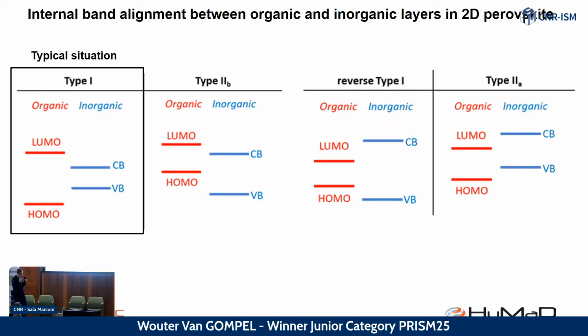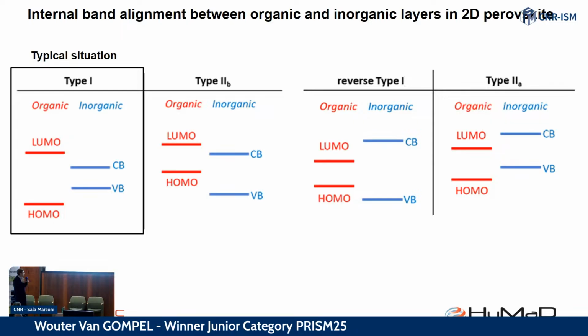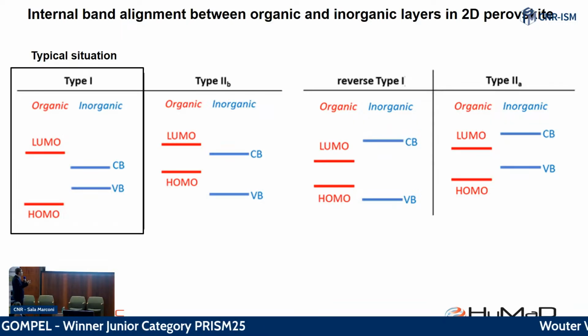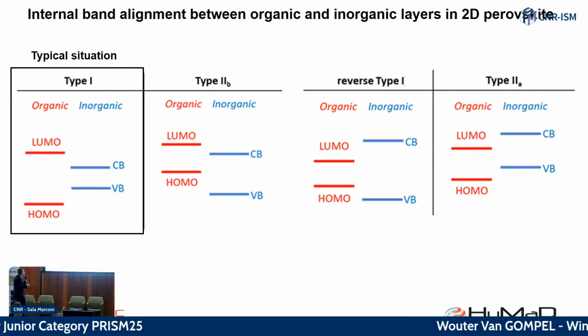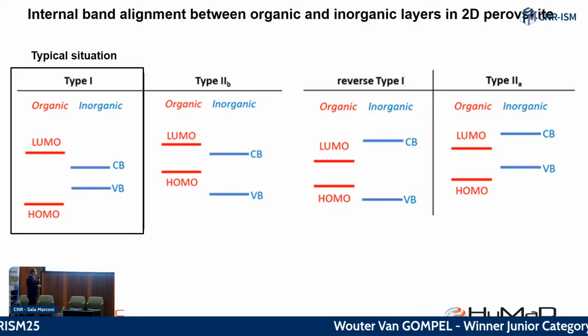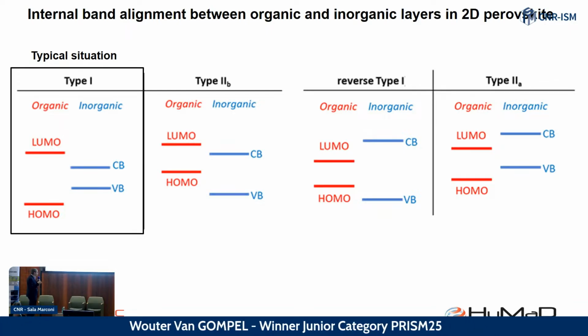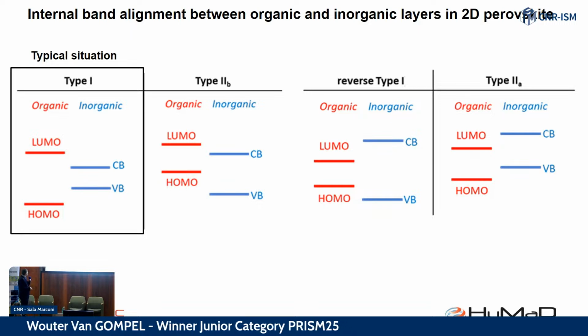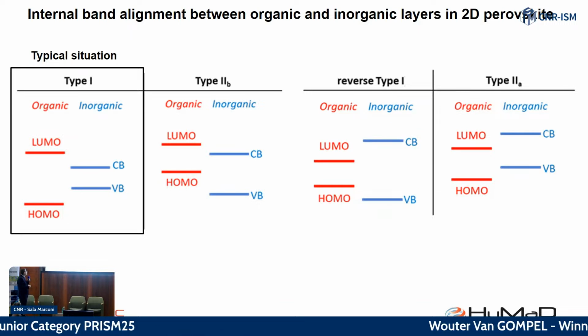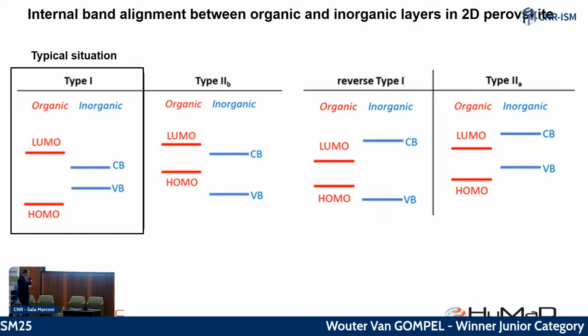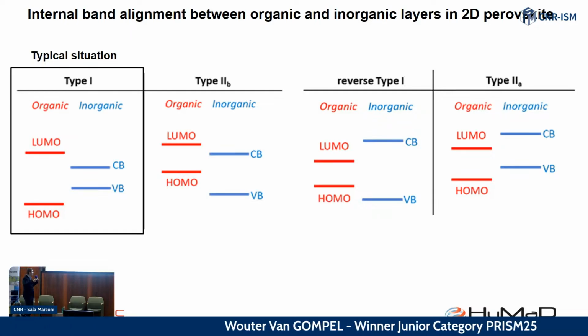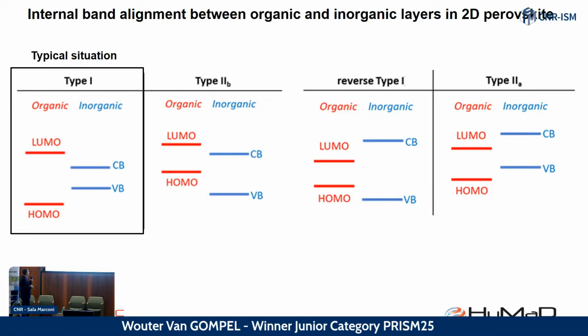But by carefully tuning the composition of the organic and the inorganic, you can get all the types of alignment that you also have in the typical heterostructures. You can think of it as a kind of heterostructure, but then internal to the material. Most are the type 1, but we also developed a couple of them that are the type 2 interface, where you get really separation of the hole and the electron over different layers.